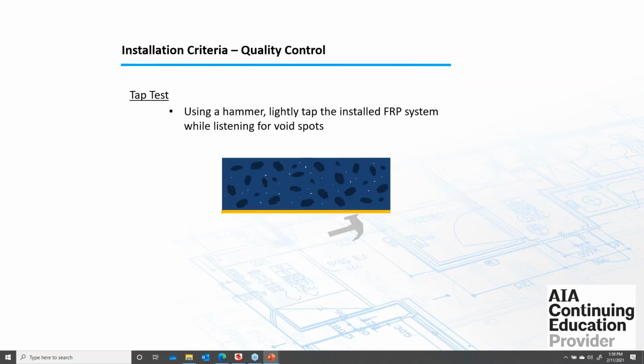Next slide. To inspect and check the quality of installation, the most famous tests are the tap test and the pull-off test. So the tap test is quite simple. Using a hammer, lightly tap the installed FRP system while listening for void spots. During the training, the manufacturers put a lot of emphasis on avoiding voids for the plates and bubbles for the wraps.